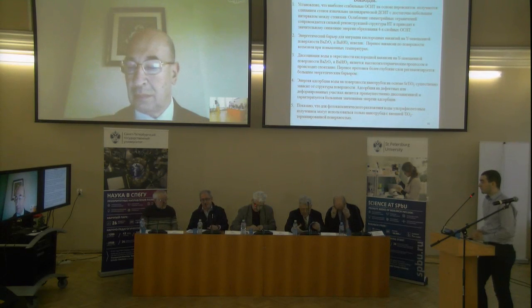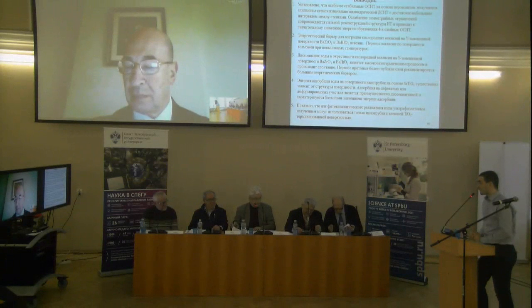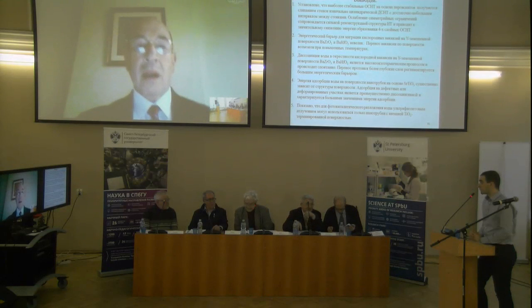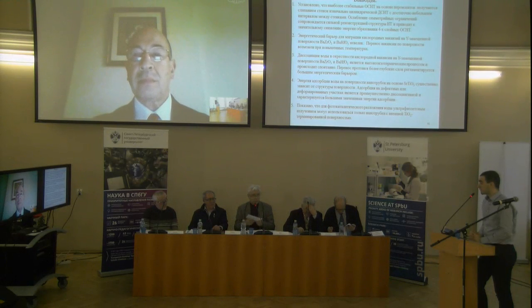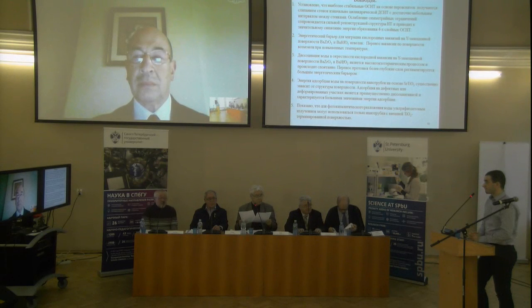Well, for my calculations, I made the basis sets of all the materials more efficient, and the diffuse functions with an exponent of less than 1/10 were excluded from this set, whereas the rest were optimized for bulk crystals. The F function of the barium atom, I should note, was excluded from the basis set because our calculations showed that it does not affect the key results anyhow.